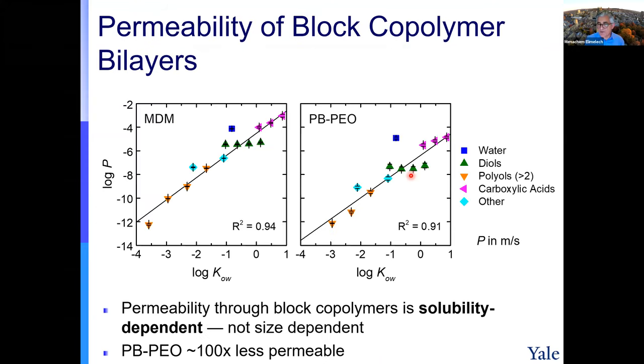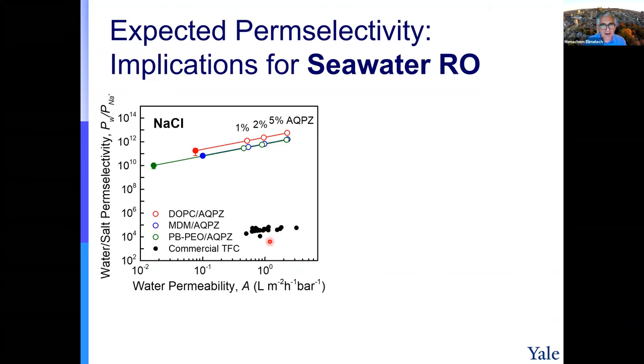We also measured it for sodium chloride and water. I did not show it to you here. With this data, we asked what the expected permselectivity would be when you deal with seawater. If we put the synthetic channel in seawater, we need to remove salt and boron, and these are relatively hydrophilic. So this was our estimation based on these measurements.